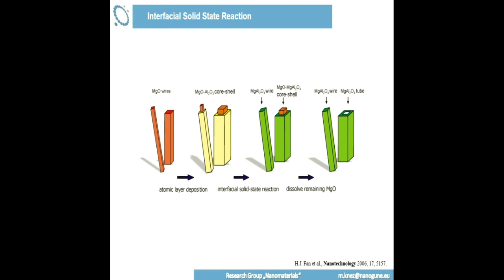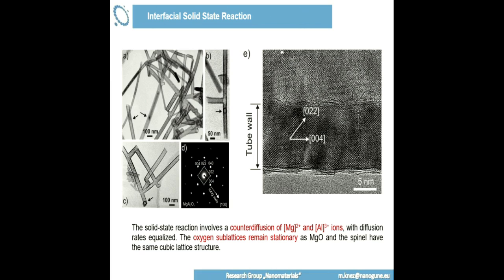In some cases, this is just an example, you will have a solid like magnesium oxide, for example, so many materials work like that, just one example. And if you coat it with aluminum oxide and you heat treat this one, you will have a migration of the magnesium oxide towards the outside and aluminum oxide towards the inside. It's a solid state interfacial diffusion reaction, and at the end you will end up with a spinel magnesium aluminum oxide, which will be a very, very nice structure. Looks like that, tubes and whatever. But you had a diffusion. That means you produced out of magnesium oxide and aluminum oxide a magnesium aluminum oxide spinel.